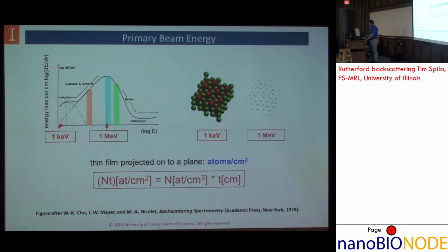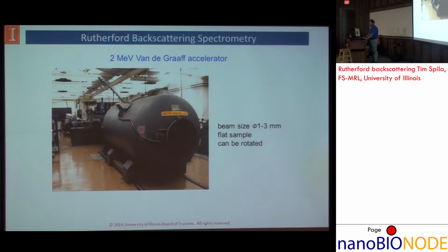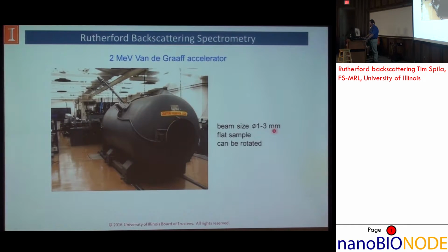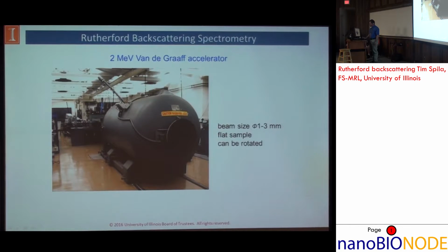This is what one looks like. We actually put it inside a big pressure vessel so we can put it up to 14 atmospheres so that we don't have the charge breaking down. This can run up to 3 MeV, at least it was designed to, but generally we do our RBS at 2 MeV. We could also do ion implantation with noble gases anywhere from 0.7 to 2.4 MeV. In general, to use this technique, we're looking at a beam size of about 1 to 3 millimeters. I know with the AFMs we were just talking about nanometers and picometers, but now we're talking about sample sizes of 1 to 3 millimeters because we have a big beam, and it needs to be flat.